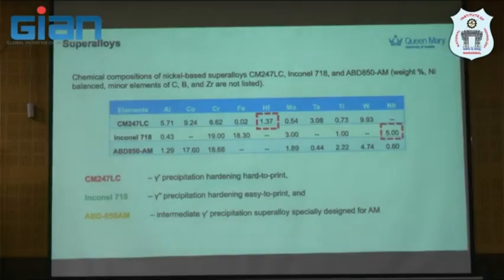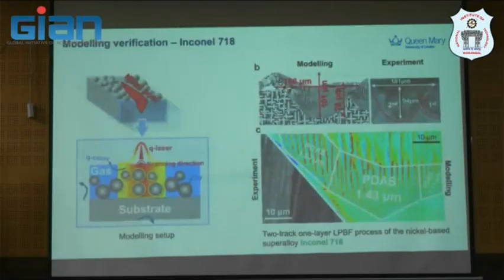Then we focus on this one, hafnium. It has only 1.3 weight percent, but instead of niobium, it's 5% here. And this is what we found. This is a verification of the model using 718. What we did, we define a calculation domain here, identified by the multi-phase solver. So that's what you've seen before, nothing fancy.